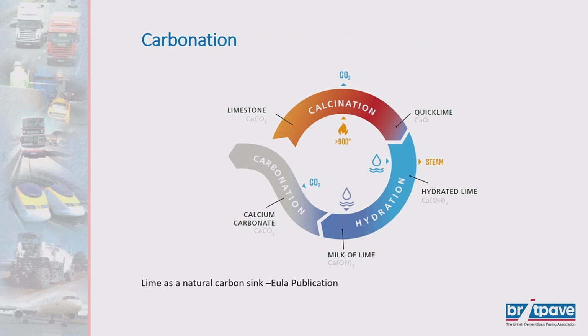Quick one on carbonation. The lime actually has a natural sink. What we call the cycle for lime starts off as calcium carbonate. Heated a lot, it turns to calcium oxide. So hydrated or milk of lime comes through. Water then comes back into it, and it turns back to calcium carbonate. Increases the strength, sorts the soil out, and sucks in CO2. This is from a European Lime Association publication. So lime can actually act as a natural sink.